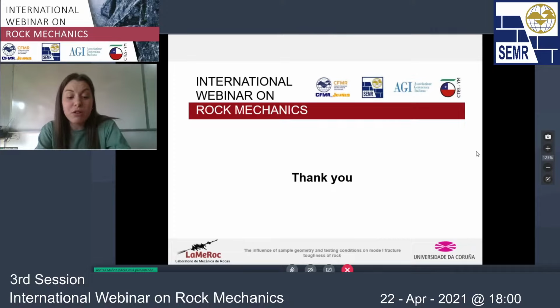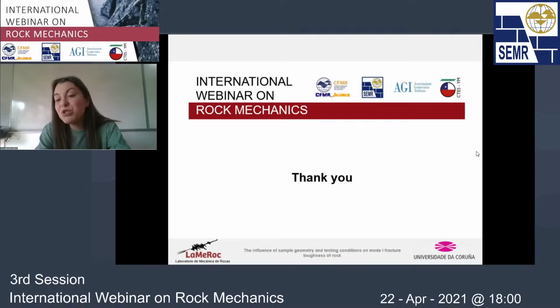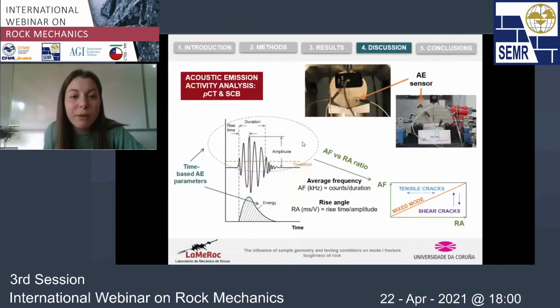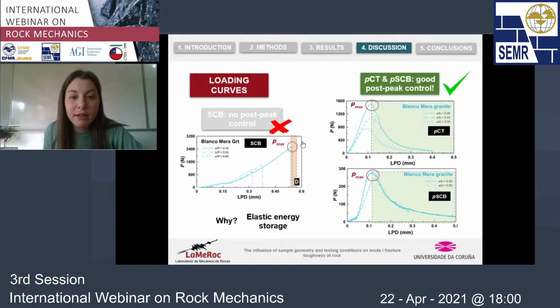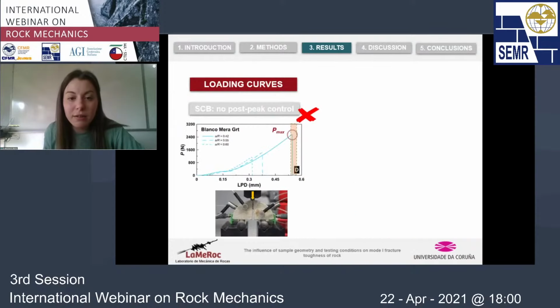And we think that it's more because when we apply the load under 3-point bending, we have huge stress concentrations at the notch tip, but also at the contact with the rollers. So we don't think that we would have better results by improving the stiffness of the device in this case. For the device for the PCT, we have measured it. I think that I didn't mention it in the presentation. Okay, so I'm going back to the picture of the device here.